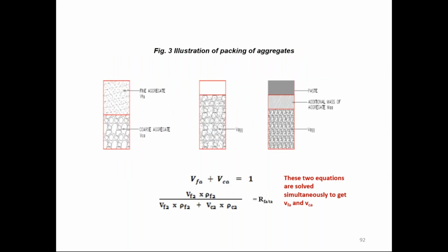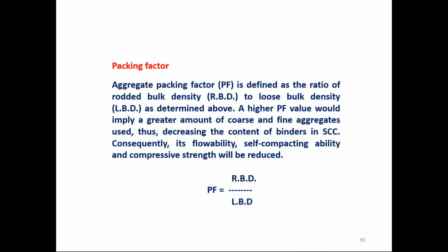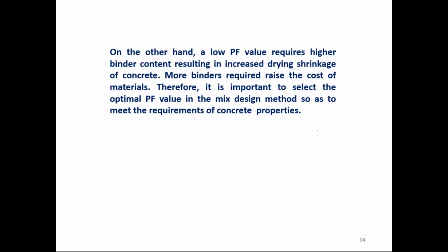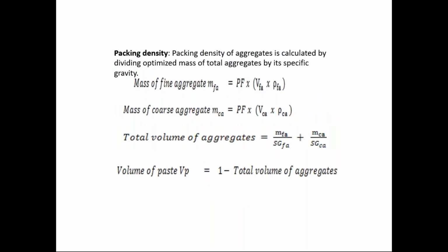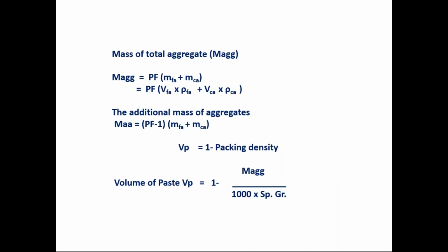We can find out the packing density by finding out the volume of each individual. You can use this particular concept to find out the packing density, and you can also find out the aggregate packing factor by dividing the rodded bulk density by loose bulk density. So finally, what we are interested in is finding out the volume of paste required when you find out the optimum packing density. Volume of paste determines how much quantity of cement you have to use. Paste is nothing but water plus cement, or if you are using any other GGBS or fly ash, that also you can include. So volume of paste is 1 minus packing density.